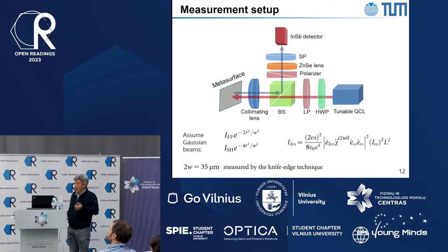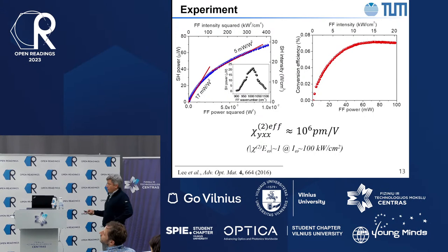So the question is, how much second harmonic radiation would such a small amount of power produce in such a thin layer of structure? Of course, we focused our beam, so we measured the beam waist and did all the calculations, and these are the results. Despite being extremely deeply sub-wavelength, and despite using tiny amounts of power, here is intensity squared, which corresponds to 10 kilowatts per square centimeter, or for the power squared, we are at 100 milliwatts squared, we already are able to produce nearly 100 microwatts of second harmonic generation, which means that our conversion efficiency is already 0.1%, and this is a huge number for such a thin structure, which was only 400 nanometers in thickness, and such low input intensities.